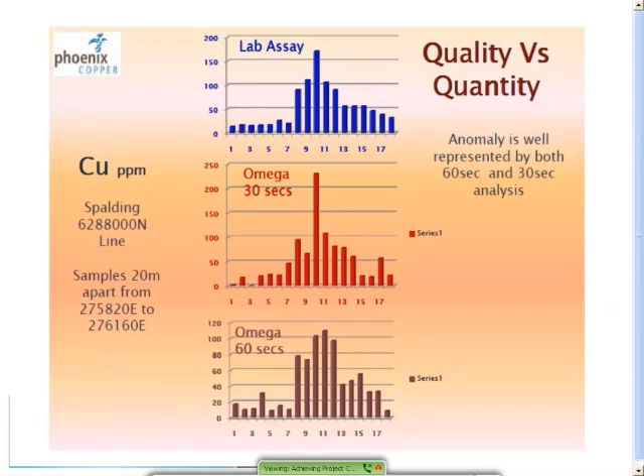Here is data from that line. What was key for Phoenix Copper here was not having the XRF produce exactly the same numbers as the laboratory, but that the anomaly is well represented by both 30 and 60-second tests when compared to the lab. This gave them the confidence and some hard data by which to base the decision to do only 30-second tests at each sample location.